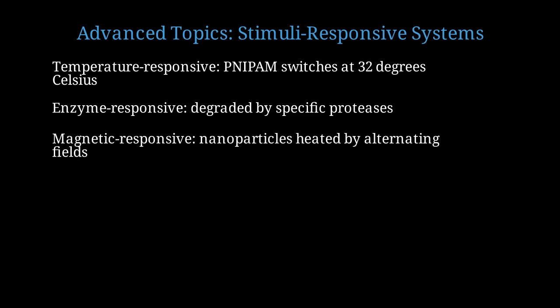Some systems use peptide cross-links that are cleaved by disease-specific enzymes. For example, matrix metalloproteinases are overexpressed in tumors. Microgels with MMP cleavable cross-links selectively release drugs at tumor sites. Incorporating magnetic nanoparticles allows external control. Applying an alternating magnetic field heats the nanoparticles, raising local temperature and triggering release from temperature-sensitive polymers. This enables on-demand, spatially controlled delivery.